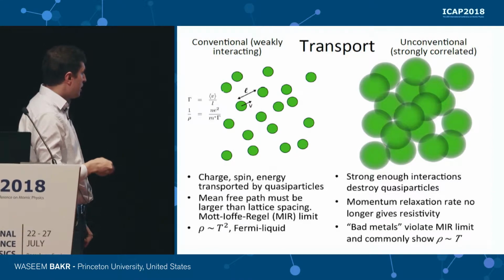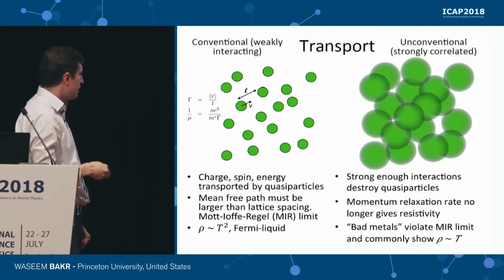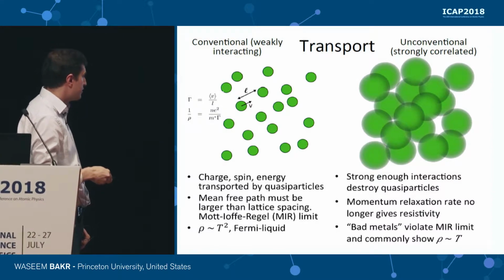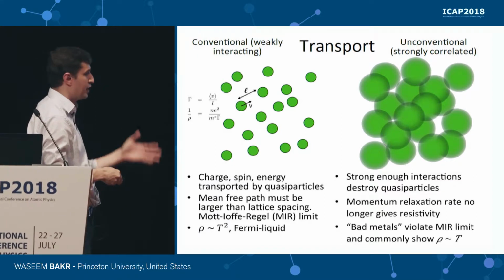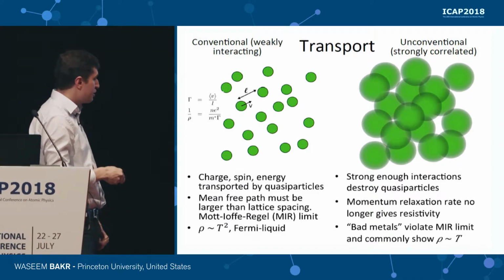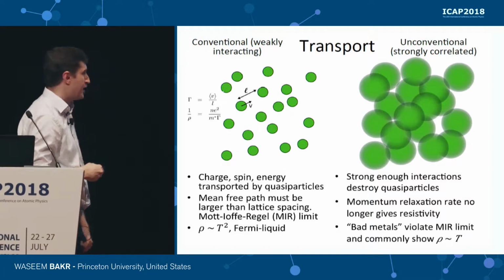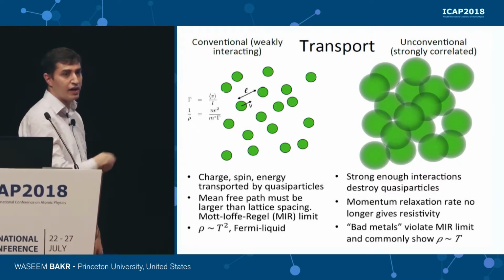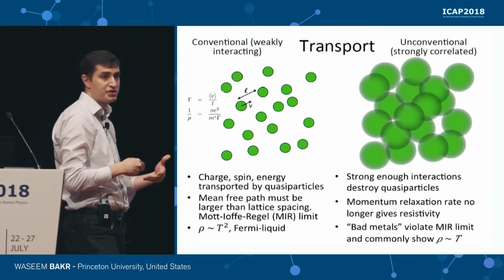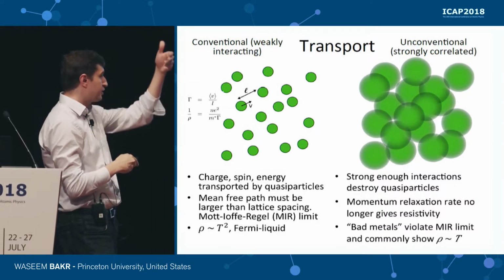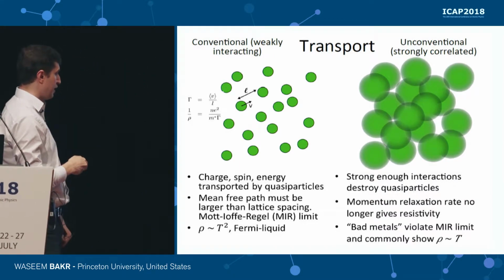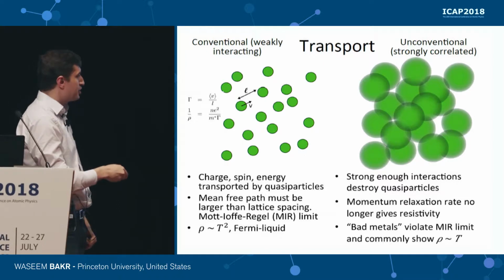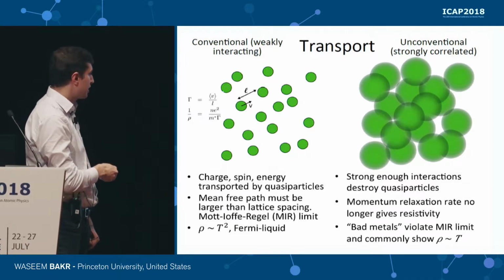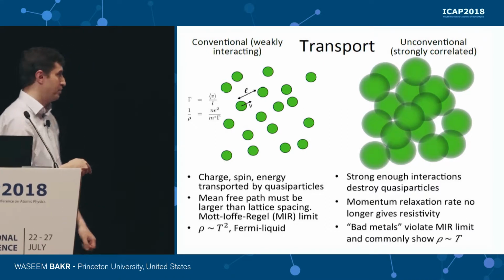In strongly interacting systems, like the cuprates or the pnictides, experimentally one observes what's known as bad metallicity. This is defined as a violation of the MIR limit. As you increase the temperature, the resistivity can increase beyond the MIR bound. And commonly in these materials, the resistivity, instead of scaling like T squared, scales linearly with the temperature.